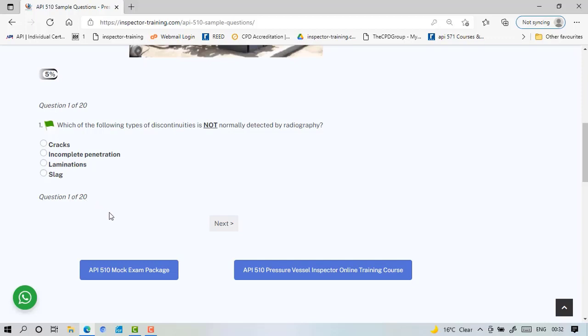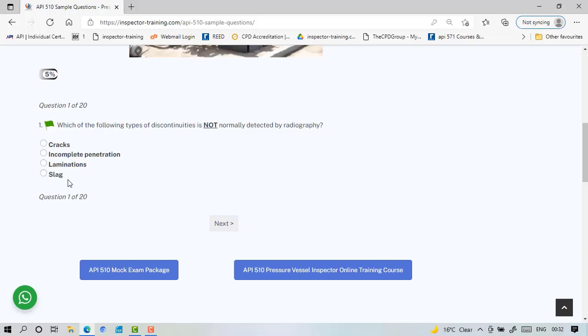Let's start with question one. Which of the following types of discontinuities is not normally detected by radiography? Now radiography is sensitive to volume because the ray passes through it. So if you got a discontinuity, normally it's less dense than the base metal, so more rays pass through and you see that place darker. Cracks still have some volume, not much but you can see the cracks. Incomplete penetration and slag have got space. Lamination is the one that doesn't have any space—it's two layers of metal not fused together. Normally you use UT lamination check for it. That's the best way to do that.